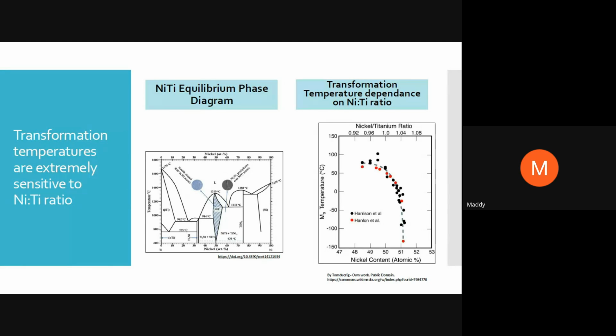The other thing I want to point out in the phase diagram is, if you look at the nickel-rich side, you can see the solvus. There's a slope over there. And what that indicates is, I was mentioning the time temperature transformation diagram, right? So based on this particular slope here, you can actually tailor what kind of precipitates, what size of precipitates, and what area fraction you can generate. So that's why you can actually generate precipitates in a nickel-rich alloy.